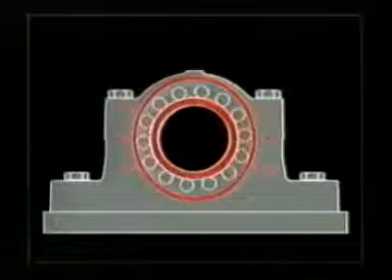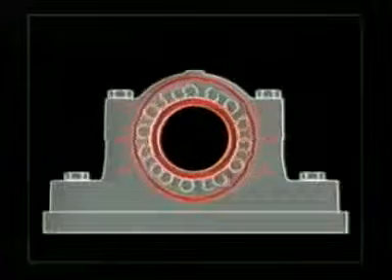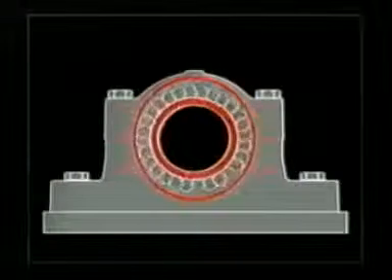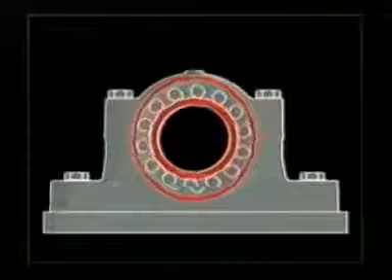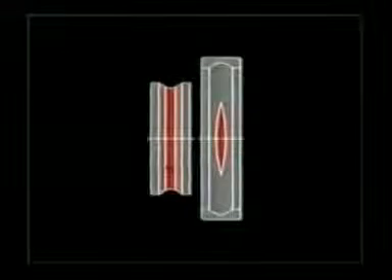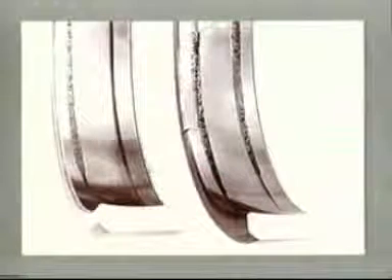Bearing rings are relatively thin-walled. They adjust their shape to the shape of the mating structure, even if that structure is oval. Under certain circumstances, however, they are so badly deformed that zones of excessive radial stress are created. This outer ring, for example, is part of a self-aligning ball bearing which landed on the junk heap before its time because of oval deformation.